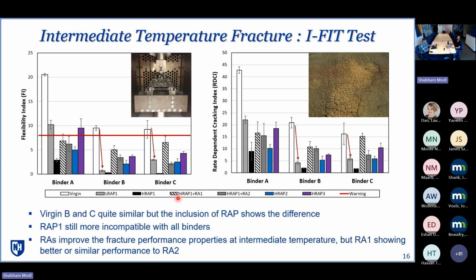On binder B and binder C side, as they have similar performance grade, we can see that binder B had a very negative impact compared to binder C on the low RAP mix side, again showing the incompatibility of binder B compared to binder C. And RAs improve the fracture performance properties at intermediate temperature, and again RA1 is showing better improvement.